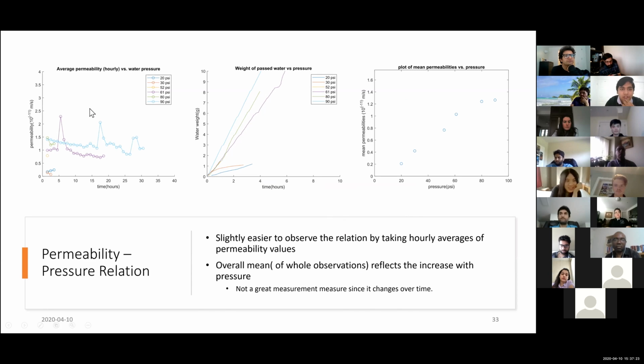So what I did was I averaged these permeability values to every hour. And in every hour, we can see that again there are kinks, which is again the high water dropping out all at once. But we can roughly see that again the higher pressure is leading to a higher water flow. This is just the weight of water. Again, we can see that a higher pressure is leading to a higher water flow. This is a plot of mean permeabilities observed over all the time. So here we can see roughly there is a linear relation.